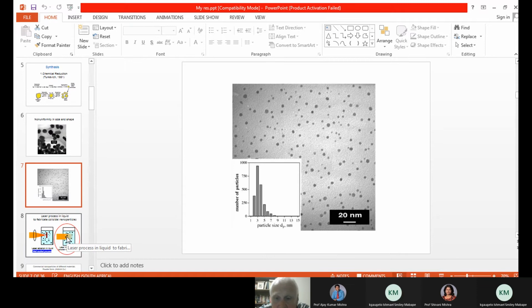And this is the result. First, our idea was, let's irradiate not a solid surface immersed in the liquid, like in laser ablation, but let's ablate colloid. We already produced nanoparticles. Let's ablate, using the same technique, our nanoparticles in colloidal form. Using such an idea, we produced these nanoparticles. All the nanoparticles are very small, and you see a very uniform size, about 4 ± 1 nanometers. But we succeeded only in producing very small nanoparticles. So the next question: if we need to produce different sizes of nanoparticles, what to do? We have to think next.